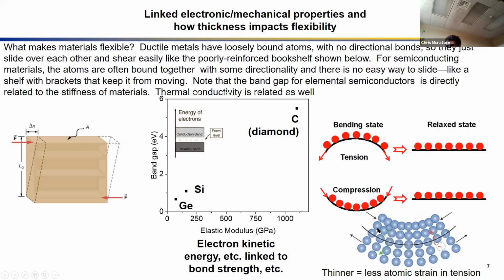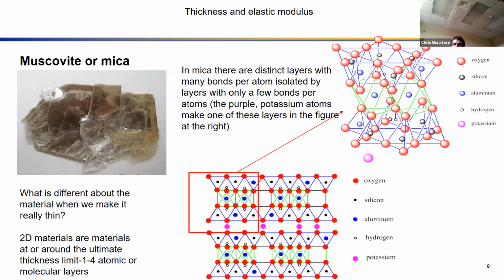Well, if I add additional layers and I bend this, and in this case, let's say I'm bending it in compression, you can see that as the thickness increases, the distance between the atoms also increases. So my strain increases with thickness. So if I want to maximize the amount of strain that I can put into a material, if I want to make a material flexible, I want to make it thin, because that's a way to minimize the distance between the atoms as it gets bent or stretched or whatever. So thin materials are a nice way to do it.